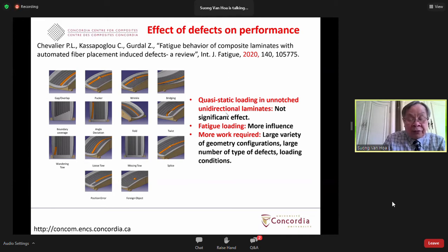However, the effect is more severe in fatigue loading, where the effect of the defect can be up to about 30%. They also mentioned that, due to the large number of defects, the different geometry configurations, and the large number of layers, the work done up to now has only looked into some very limited configurations, and a lot more work needs to be done before we can really understand the effect of the defects.